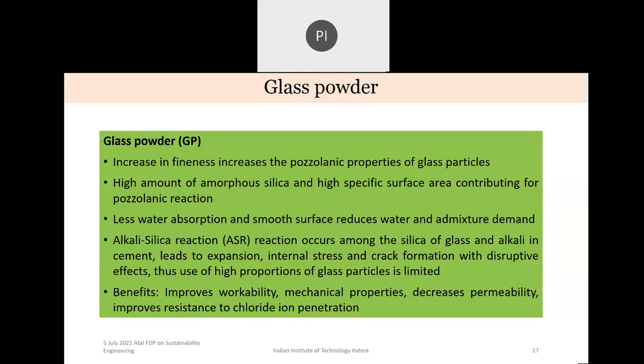Now, this alkali silica reaction occurs between the silica of glass and the alkali present in cement, and leads to expansion, internal stress, and crack formation with a disruptive effect. Thus, the use of a high proportion of glass particles is limited because, as we were discussing earlier, alkali silica reaction is detrimental to the durability of the concrete. Glass powder is a sustainable material, but it is causing alkali silica reaction. So we cannot use this for a very high replacement level. So we have to properly calibrate, or properly find out the optimum dose up to which the alkali silica reaction resulting from the use of glass powder does not affect the durability of the concrete.